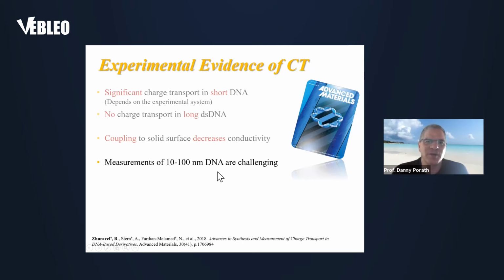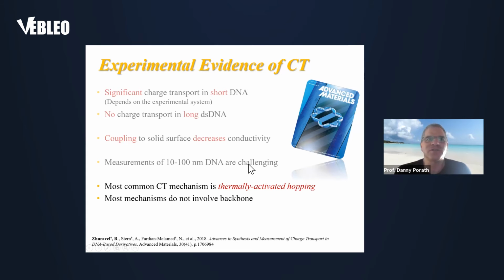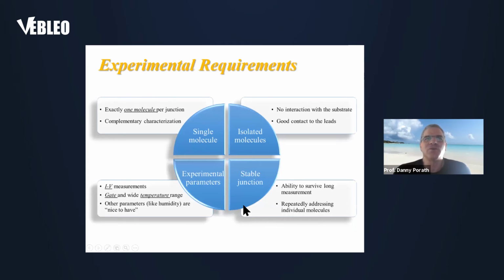Most of the experiments published before were done either on shorter than 10 nanometers, usually in break junction systems or STM, and longer ones were done on hard surfaces. The most common charge transport mechanism was thermally activated hopping, and most of the mechanisms did not involve the backbone. So the question was, what is needed in order to do a good experiment in which we know we address all the challenges that I mentioned before?